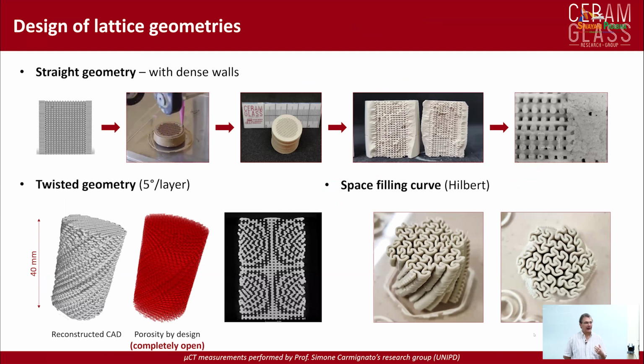One of our PhD students started working on printing paths. I told you that with direct inking, the tip needs to follow a continuous path because it is virtually impossible to work with a start and stop approach. And this gives you some limitations in terms of the structures that you can print, but it also provides some opportunities. So he has been working on generating structures using fractal geometries. And these provide some advantages, for instance, in terms of permeability with respect to scaffold structures, without compromising the strength.